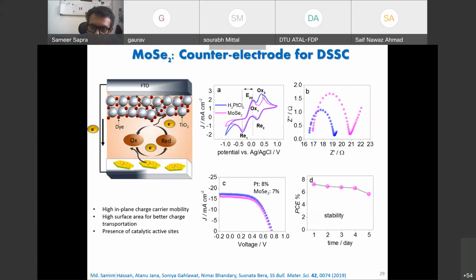And these two peaks essentially are the oxidation and these two are the reduction peaks. And with platinum, the blue one, and with molybdenum selenide, I see that both these oxidation and reduction processes can be catalyzed. The only thing is that platinum is more conductive, MoSe2 is less conductive. And because of that, when we make these solar cells and study the current-voltage characteristics, what we get is 8% efficiency with platinum and 7% efficiency with molybdenum selenide. We've not harped too much on the stability issues, but we did study for a few days, 5 days, and they tend to be decently stable. Dye-sensitized solar cells are stable for years.